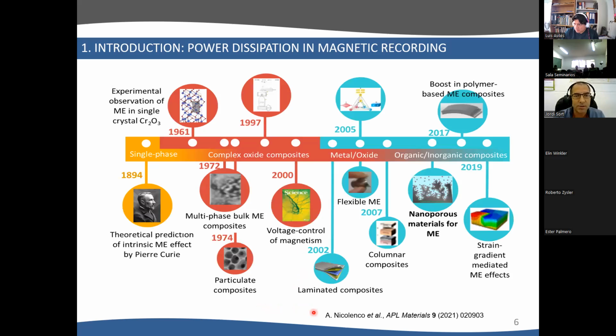And actually, this brings us to the field of magnetoelectricity. This was predicted in 1894 by Pierre Curie, who predicted the intrinsic magnetoelectric effect. So in some materials the magnetic and electric orders can be coupled to each other, so that, for example, you can control electric properties with magnetic fields and vice versa. The first experimental observation of the magnetoelectric effect was done in 1961 in chromium oxide. And from then, there have been a number of materials, including single phase, but also composites, where you can use voltage to control the magnetic properties.